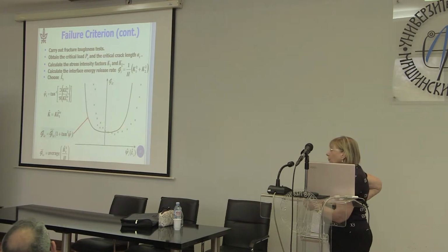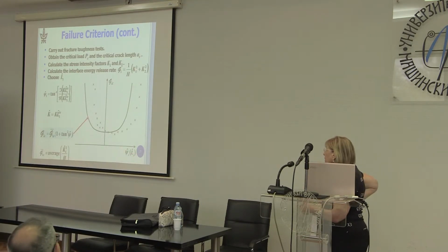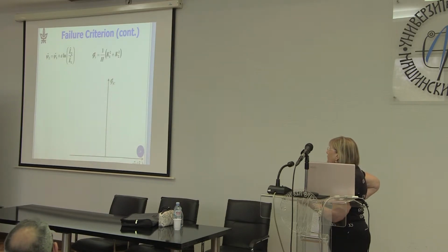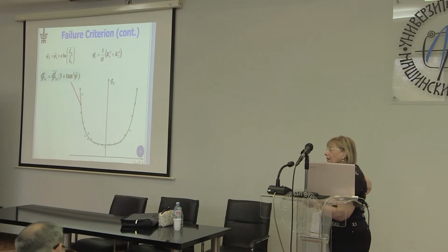And we see that the shapes are rather similar, but they don't match. So what we do is we go into our basket of techniques, and we remember that we can translate the psi axis depending on L hat. So we choose L hat. I mean, we do this in the computer. We change L hat, and this gives us psi 2. And now you can see this is psi 2 for L2. And now it fits pretty well. And so we're able to translate this axis and get our data to fit this.